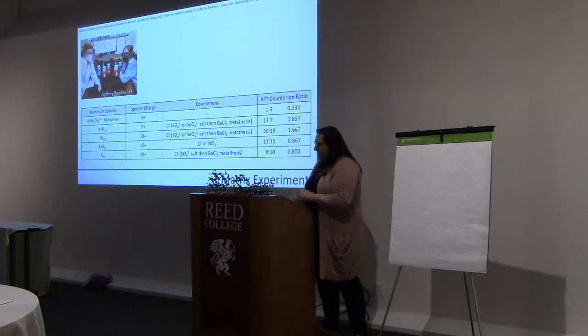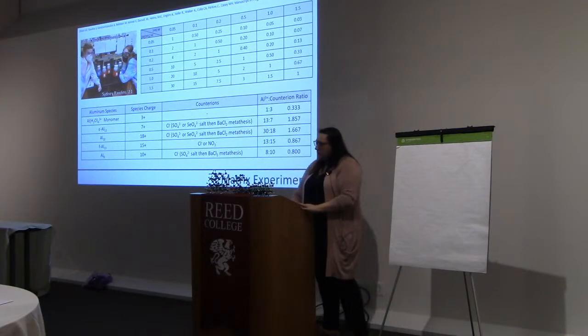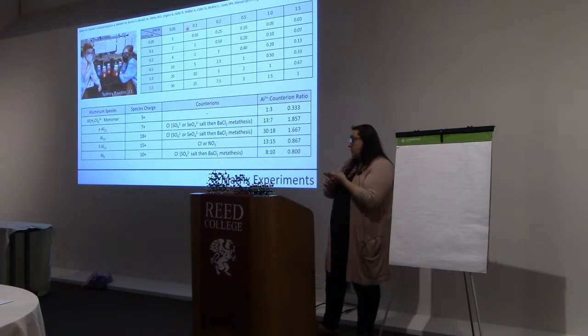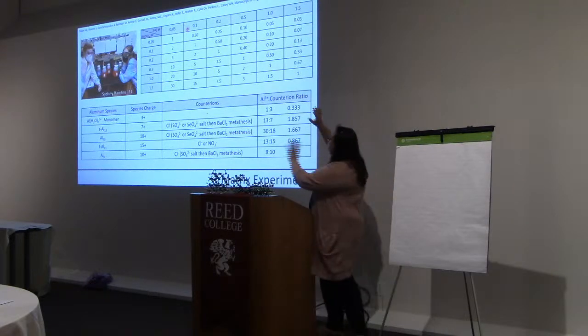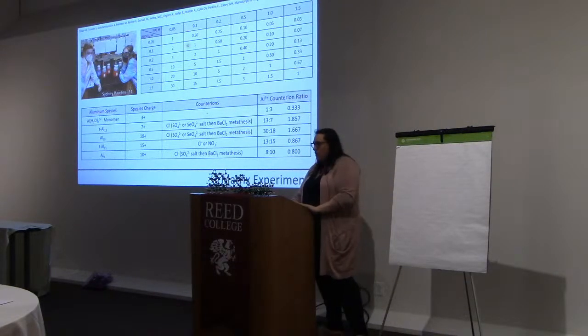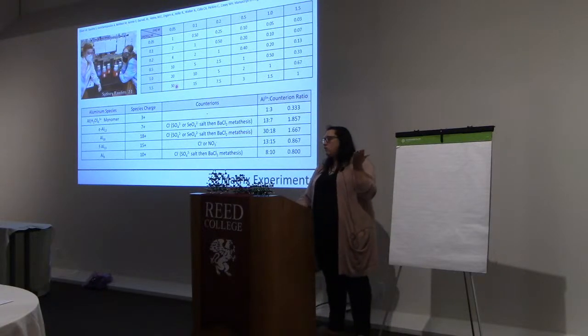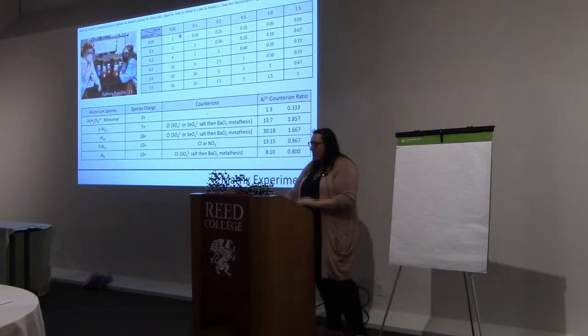So we developed this matrix where we took aluminum hydroxide at different concentrations and an acid, HCl or nitric acid, at different concentrations, and created ratios. So we have this nice 1-to-1 region down the middle, then we have some less than 1, some greater than 1, and then there's the extremes, right, where nothing's going to dissolve here. We're not going to be able to get 1.5 molar aluminum hydroxide in 0.05 HCl. It's just not going to dissolve, but it's part of our matrix.